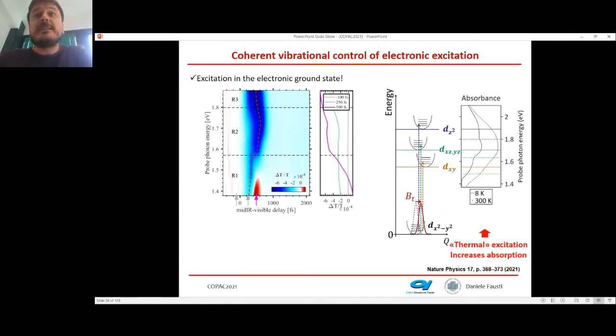On the other hand, if you coherently drive the structure, as we have done, in the electronic ground state, you can find regions of induced transparency. Basically, this is a new kind of interaction where you have a coherent interaction between two different fields, one of which is the elastic field of the material. So it's the elastic field that actually makes the electronic excitation transparent. It's a first example that by resonantly driving the structure in the electronic ground state, you can trigger the formation of some order in the electrons, because you can freeze an absorption which was there due to the thermal excitation of the phonons, and you can control it coherently by controlling the elastic field in the material.